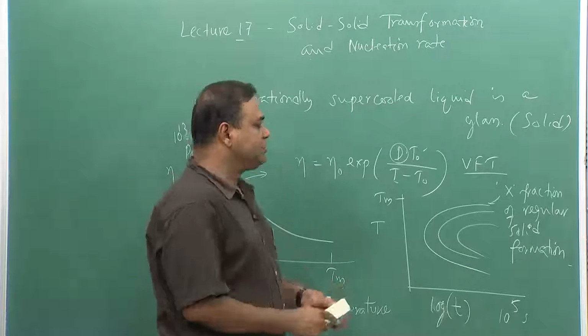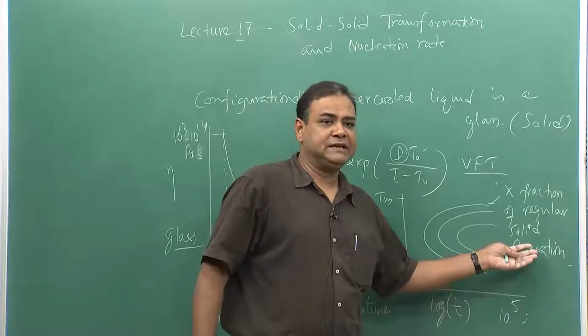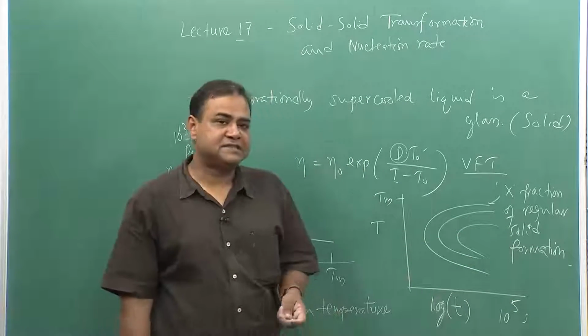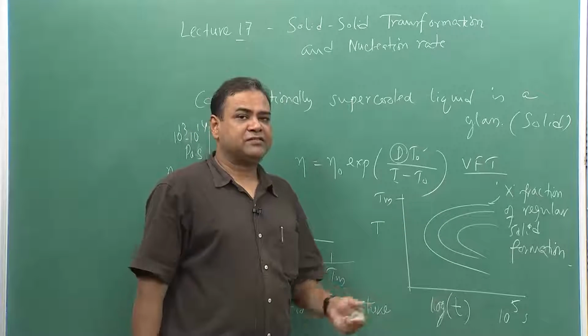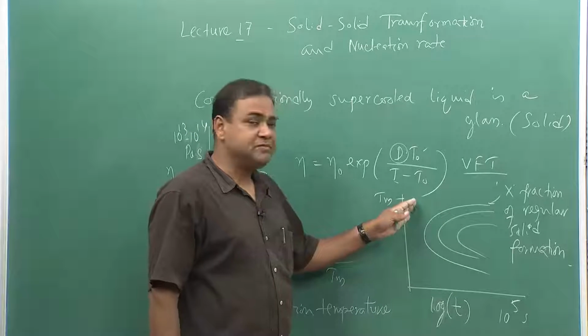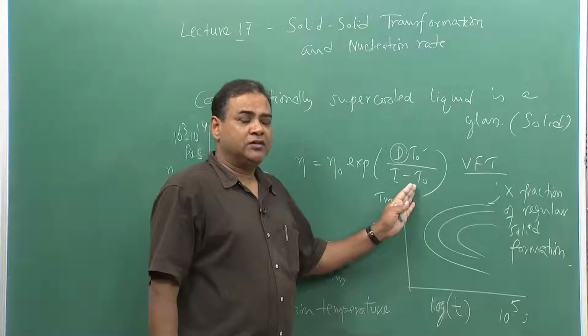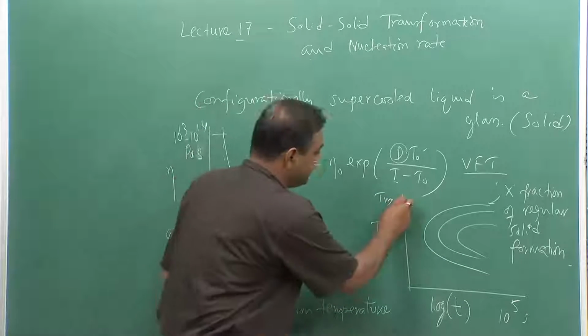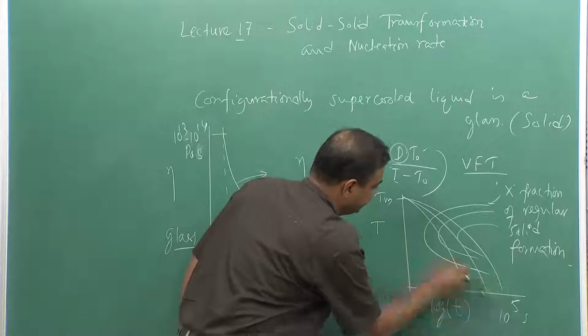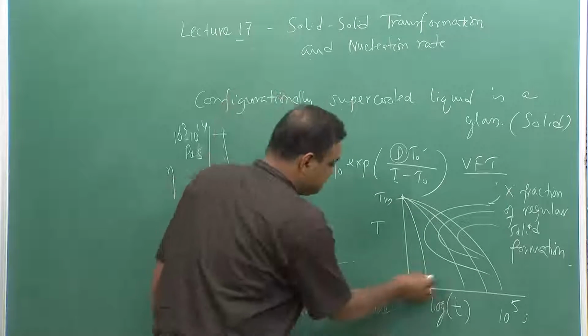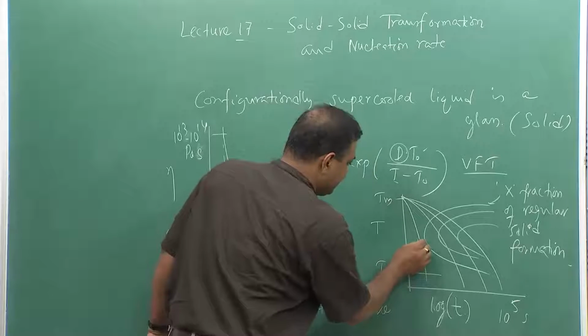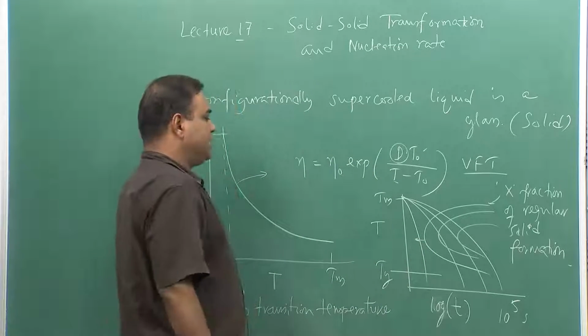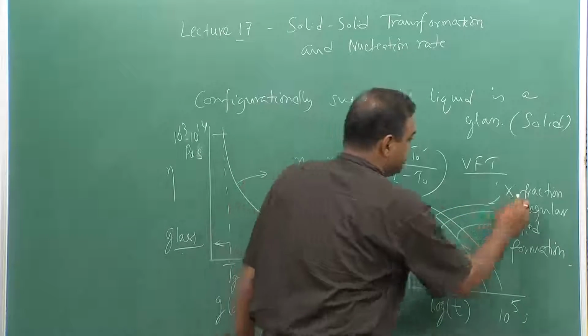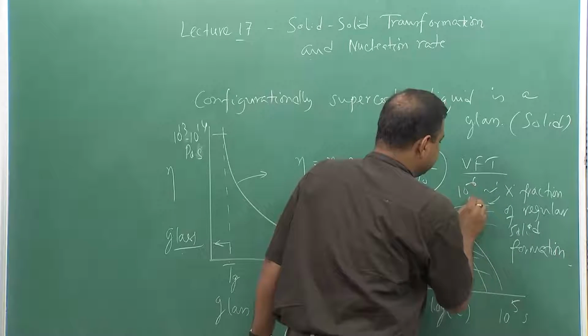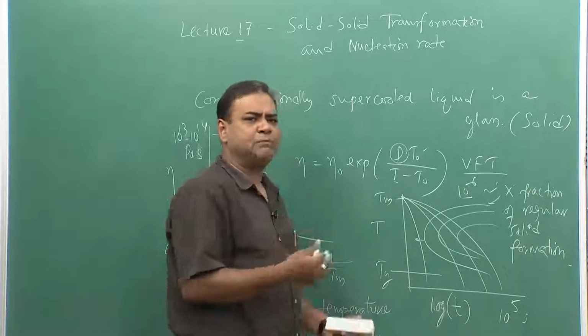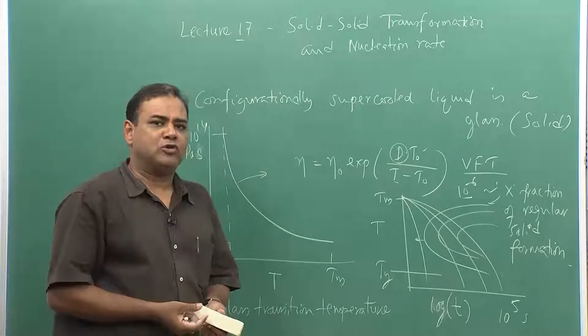Regular solid means it's basically crystal. In case of metallic systems, we do experience crystal and liquid-to-glass transition, and at the same time liquid-to-solid transformation at a different heating rate. For example, if I see the heating rate, then if this is my Tg, below this particular x value, if this x value is close to 10 to the power minus 6, then we say that below that point we cannot measure the amount of crystal.